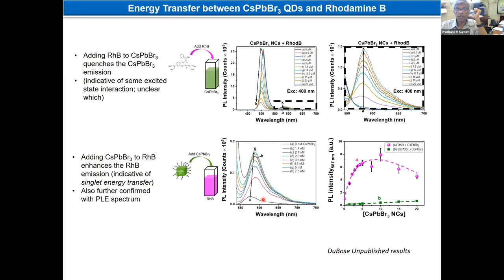We can also do the reverse way. We can keep the rhodamine B concentration constant and increase the cesium lead bromide so that more light is absorbed by cesium lead bromide. In that case also, we see this enhancement in the rhodamine B emission. So note that here rhodamine B is constant. And we can calculate the enhancement, and about a factor of 7 enhancement we see. And as you increase more, there is again internal absorption, and we start seeing a decrease.